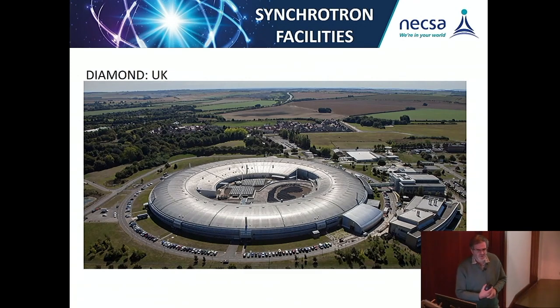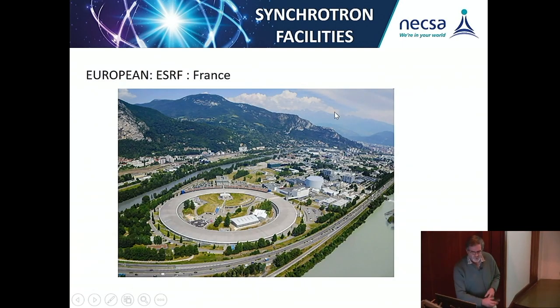Because on these machines you end up with a photon flux of 10 to the 20 photons per square centimeter per second, a scan of half an hour can be done in 1 minute at those machines. But they also have improved resolution, especially the European Synchrotron Radiation Facility in France, where South Africa has a collaboration where researchers can go to that machine, apply for beam time, and utilize those. But the problem is that those machines are overbooked, 5 times overbooked.